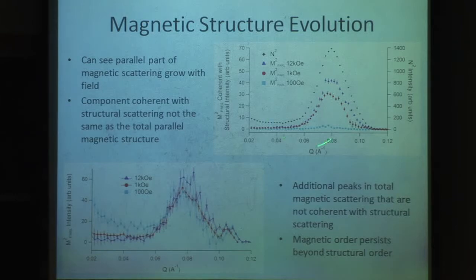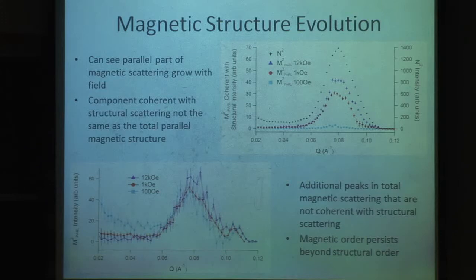And this component of it is the one coherent with our structural scattering. And that one looks different than our part that is incoherent, or is not dependent on our structural scattering. This one that is not coherent with our structural scattering has additional structure. It has this nice little peak here that is not shown in this one. So we're trying to figure out why that happens. There's this additional order from this peak, because the peaks show order, that's not present when we look at what's going on with the structural order, which means that there's more magnetic order present that's not present in the crystal structure itself.